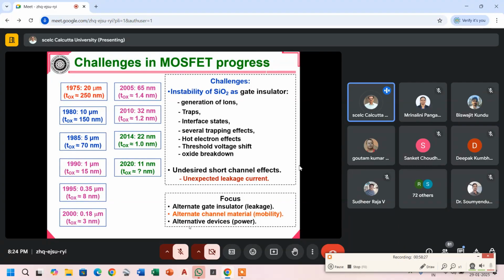When the gate length is 350 nanometer, the oxide thickness was 8 nanometer. In 2000, it was the 180 nanometer MOSFET node, where the oxide thickness came down to 3 nanometer. And in 2005, the 65 nanometer gate length MOSFET was introduced, where oxide thickness is taken to be 1.4 nanometer, and so on. Now, it is the 11 nanometer gate length and MOSFET oxide thickness.